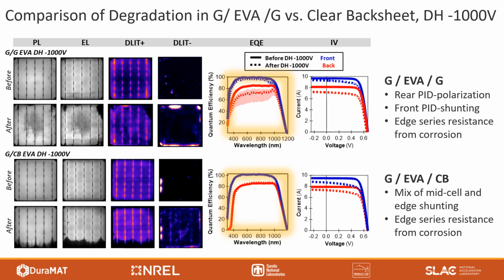So I actually find it really interesting that neither of these resistance type effects, like the series resistance or the shunting, seem to show up significantly in the EQE curves. That's especially obvious for the glass clear backsheet sample. And I believe what this is telling us is that our EQE curves are dominated more by the semiconductor quality and the efficiency of light absorption rather than changes in the resistance parameters.